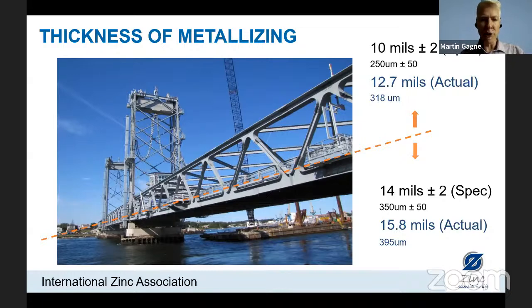So I've added the orange dash line to this image here. So we can see below the specification was for 14 mils or 350 microns of zinc, and 15.8 or almost 400 microns of zinc on average was applied to this section of the bridge. And then above the bridge deck, specification was 10 mils or 250 microns, and in actual fact, 12.7 or 318 microns on average was applied to the top surface of this bridge.